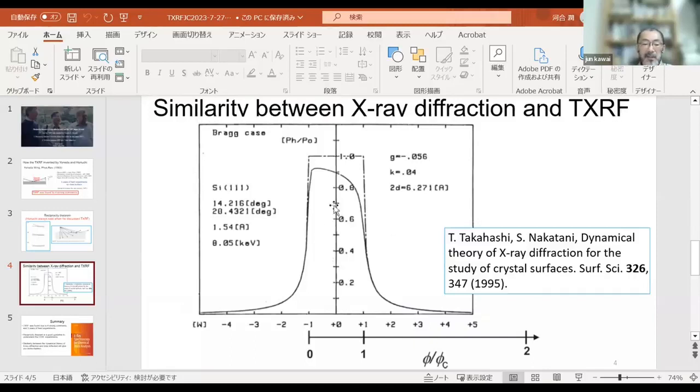So this is a Darwin curve of X-ray diffraction. This is a silicon 111 single crystal, big crystal, and this is the Bragg angle. And this is the silicon hat profile without X-ray absorption, and this is with X-ray absorption. So if we use the dynamical theory of X-ray diffraction, the diffraction peak has some width, and if the absorption exists, then this kind of line shape is calculated, completely theoretically, using the dynamical theory of X-ray diffraction. And Takahashi and Nakatani published a paper in